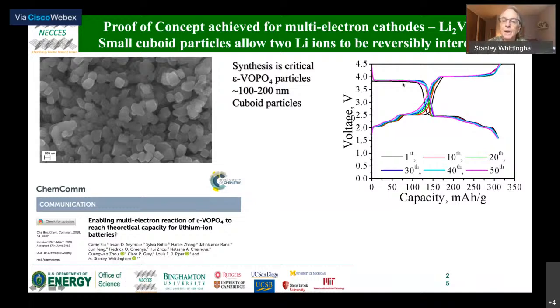Now, the key point to note here is the black curve is the first cycle. The purple curve is the 50th cycle. There's no difference. So we have now proof of concept. We can stuff or intercalate 2 lithium ions into a crystalline lattice without hurting that lattice in any manner. So we've got proof of principle here.